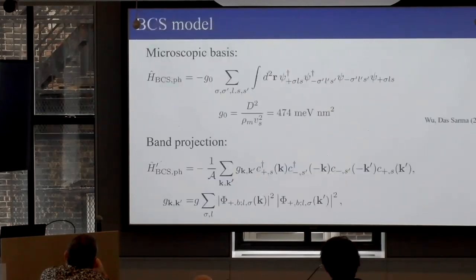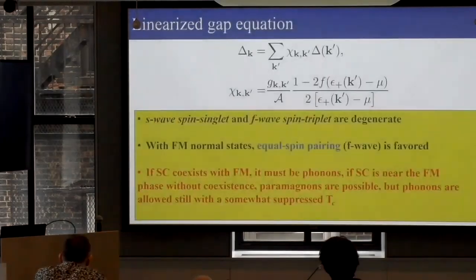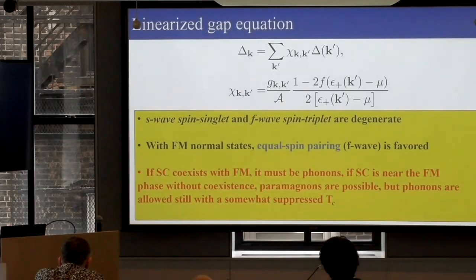So we then do a calculation. Yang-Zhi Chou did a huge calculation doing band projection, and then using the BCS thing. I'll come to whether we do full Eliashberg or not. And so this is a linearized gap equation. I'm still talking about BCS. Then we solved it numerically. And what we find is that superconductivity is actually in the same regime where he's finding ferromagnetism. Okay. But this means that it has to be phonons, if superconductivity and ferromagnetism are together. If the superconductor is near a ferromagnetic phase, then you have a lot of fluctuations, then paramagnons are possible.